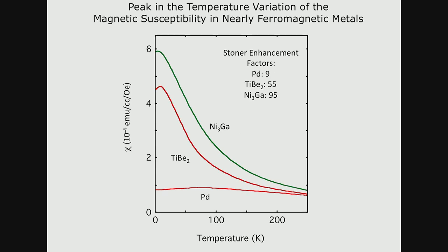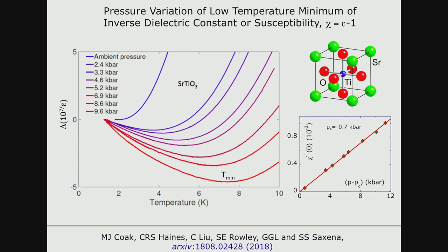Here are a few cases among relatively simple d-metals on the border of ferromagnetism, where the Stoner enhancement factor — closely related to the Wilson ratio — varies from about 10 to 100. Although the peaks are very weak, they are completely reproducible and seen many times. We see the peak position shifting down towards zero as you approach the ferromagnetic critical point. This phenomenon has been seen with even greater precision on the border of ferroelectrics, in particular in recent data on strontium titanate, which is right at the edge of being a ferroelectric — with a tiny negative pressure, it goes into a ferroelectric state.